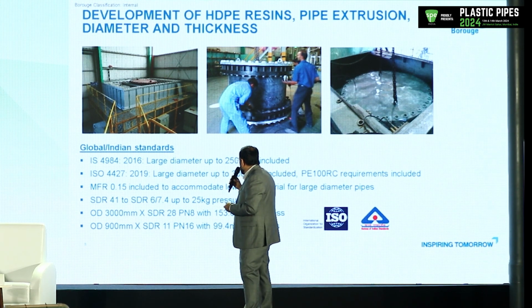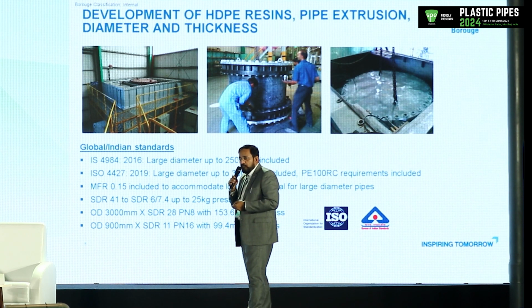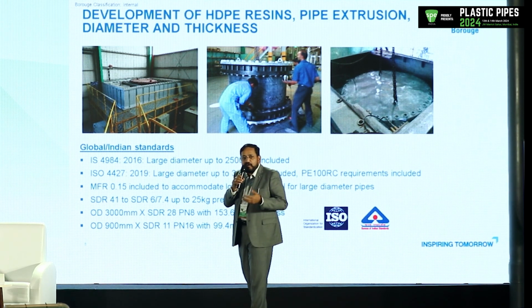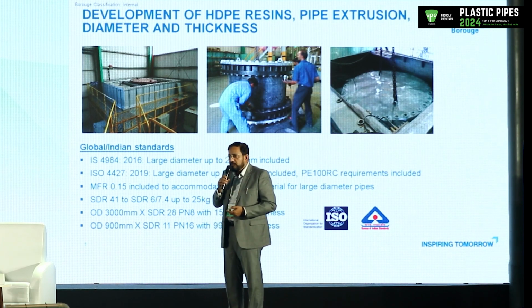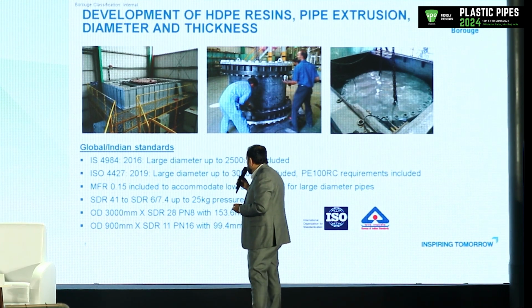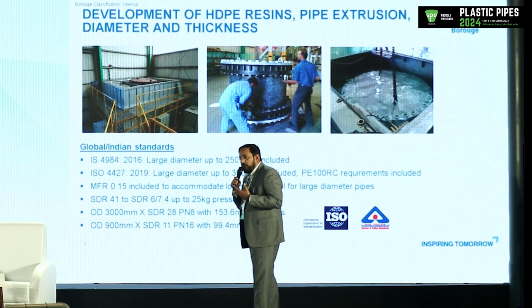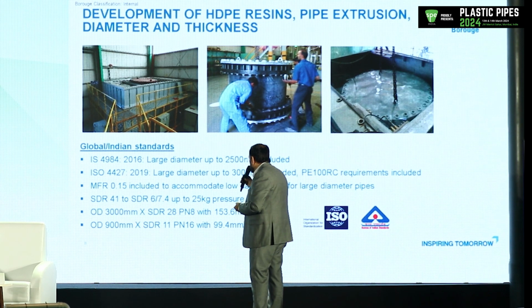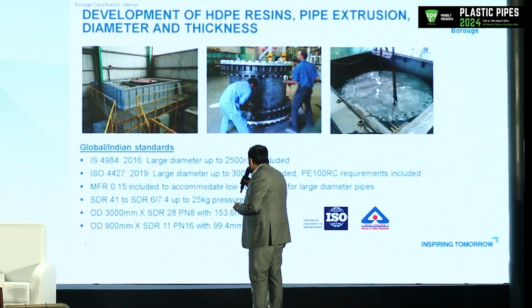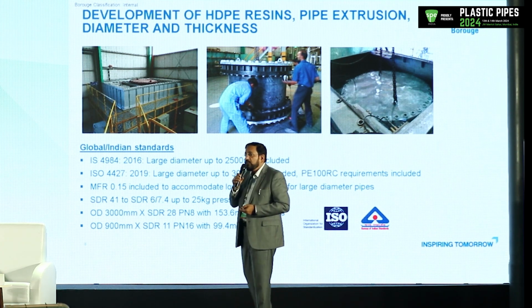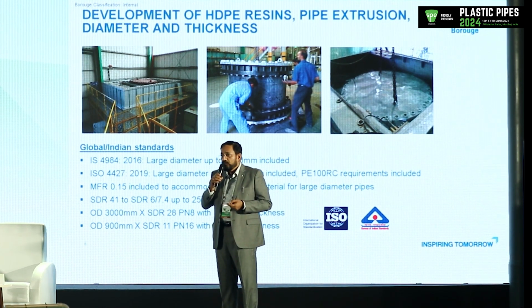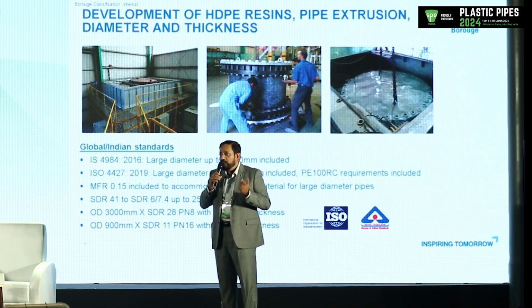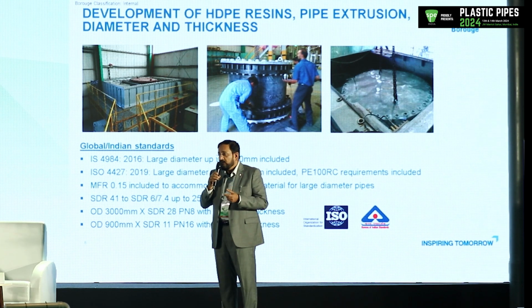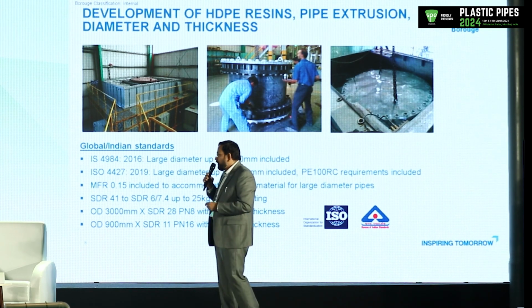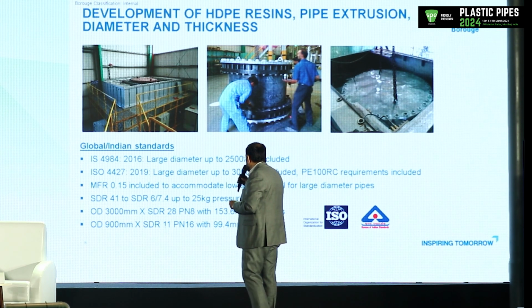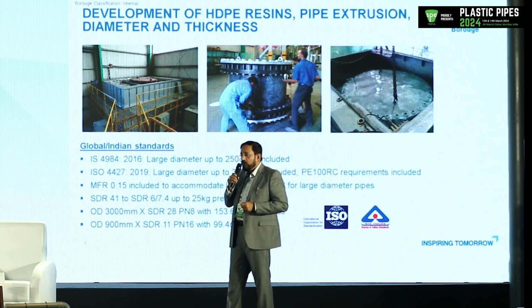So then we have pipes talking about 25 kg. People used to say plastic pipe can't go beyond 8 or 10 kg or 16 kg. Now we are talking about 25 kg pressure applications. Just to give you an idea, when you talk of thicker pipes, 3000 mm SDR 28 is a PN8 pipe with a thickness of 153. People talk about 160 mm pipe or 140 mm diameter pipe. Now we are talking about 160 mm thick pipe. Even the 900 SDR11 PN16 will have a thickness of around 100 mm.